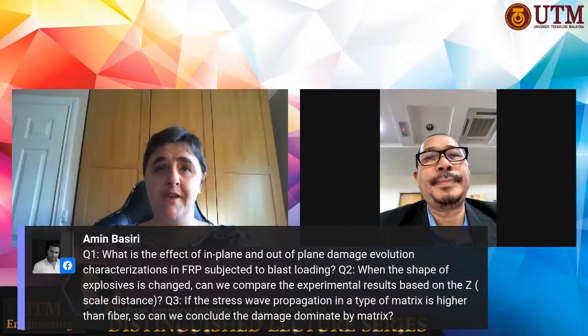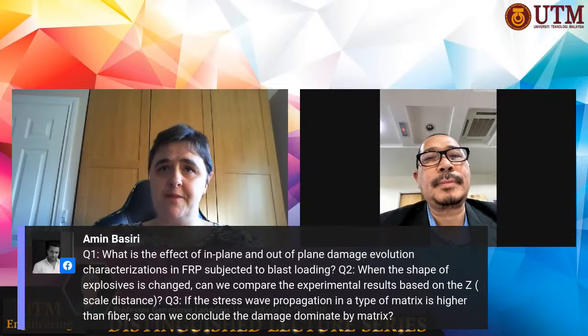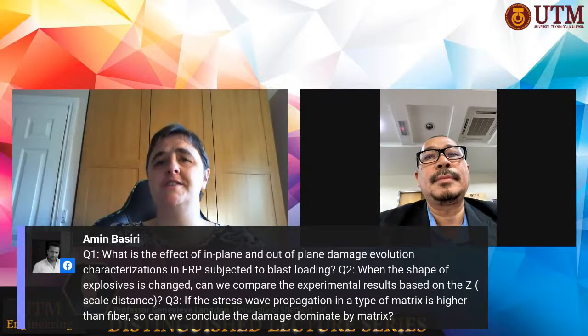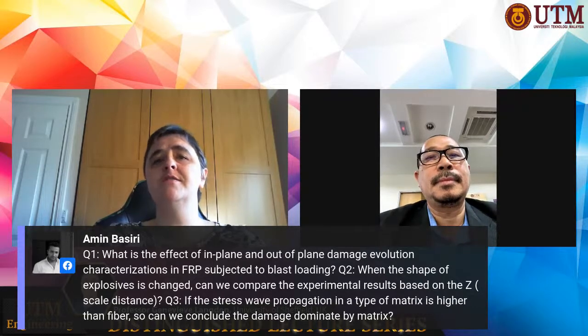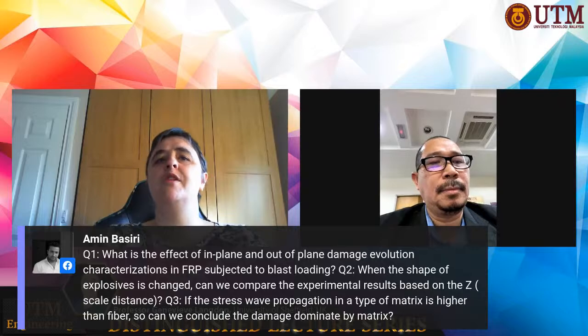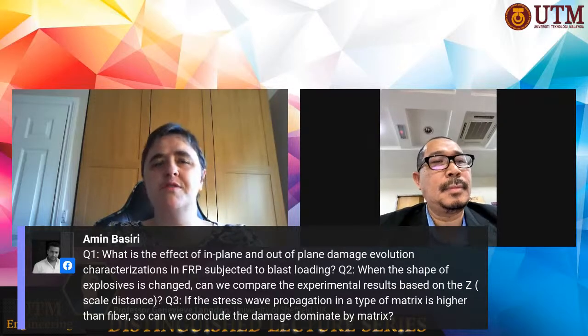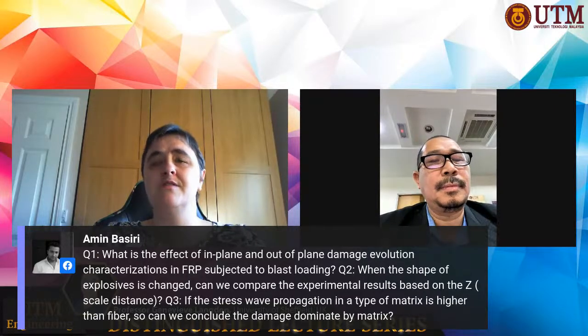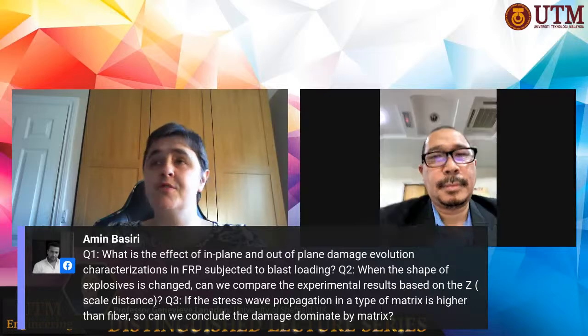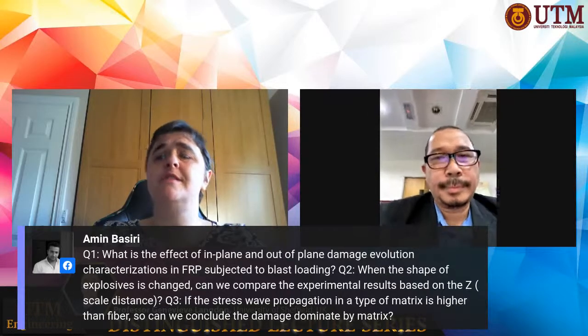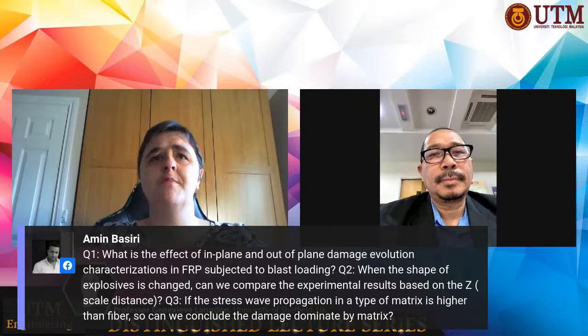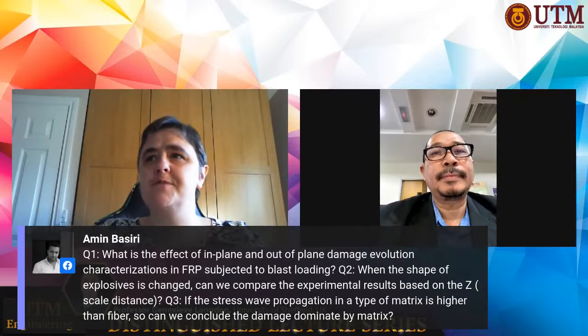So the stress wave propagation through the fiber is generally more dominating than through the matrix. The matrix is going to get badly damaged whatever we do, because the matrix is almost always going to be weaker than the fiber itself, unless you're talking about natural fibers, in which case the matrix does play a bigger part. I hope that was helpful, Amin.